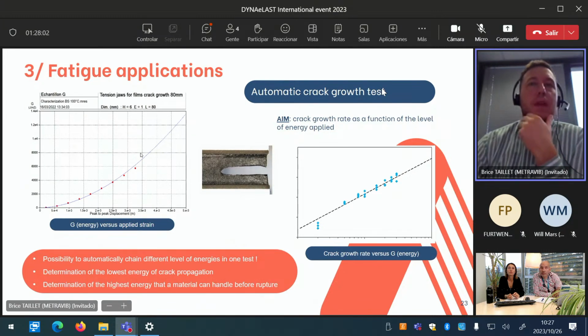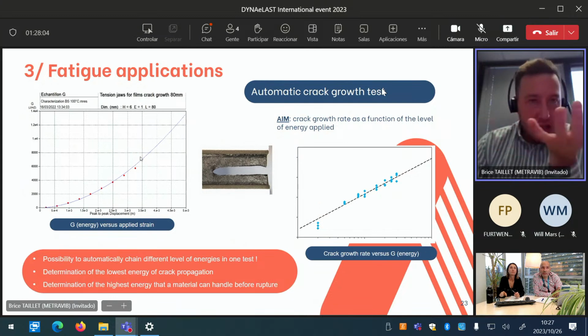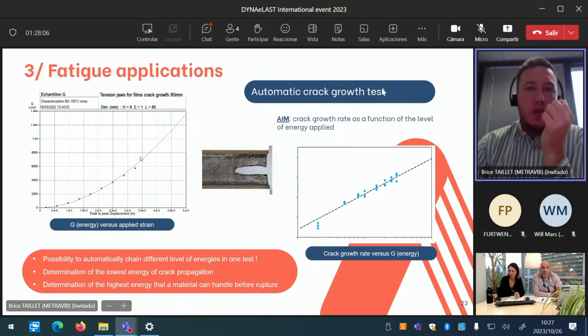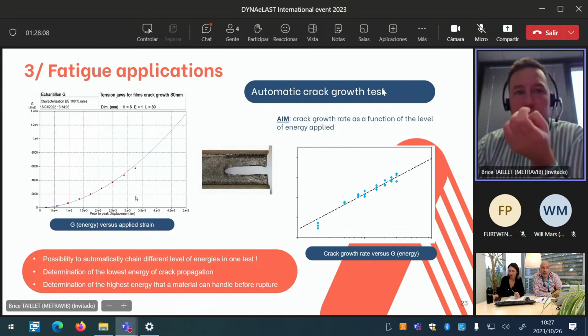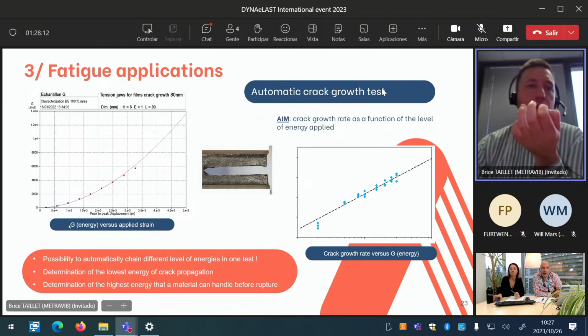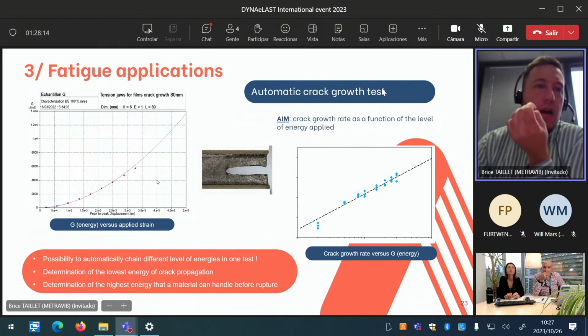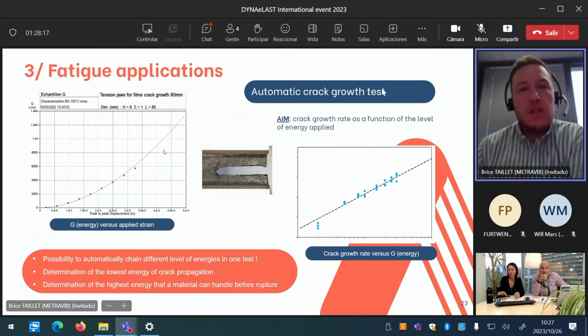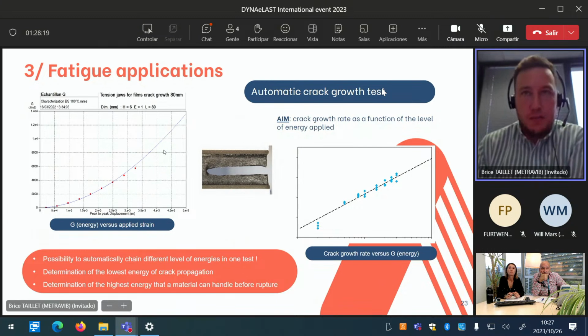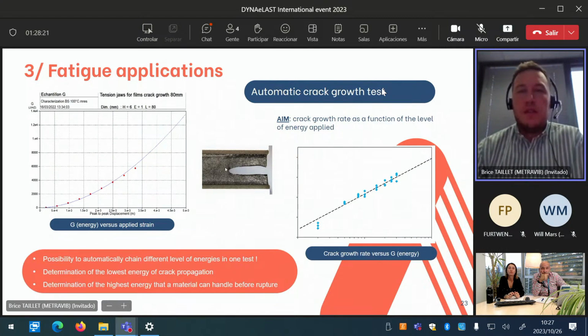Okay, so we are able to automatically chain different levels of energy in one test. We're able to determine the lowest energy for crack propagation, and we are able as well to determine the highest energy that a material can handle before rupture. You can see a short animation with this kind of test.